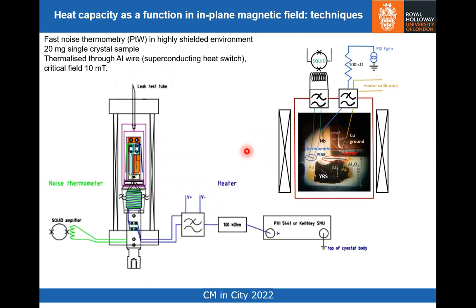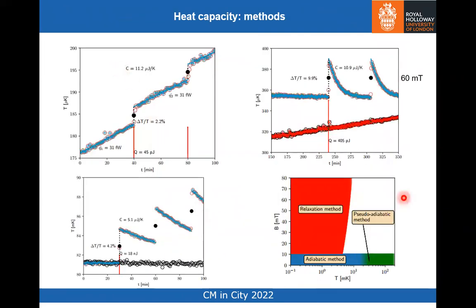So this is primarily a theoretical audience, so I won't dwell on these slides, but we use fast noise thermometry. Noise thermometry has never been used for heat capacity measurements before. It has to be fast, as you'll see in a minute. We're doing measurements on a tiny sample, 20 milligrams. It's thermalized through an aluminium wire, which acts as a superconducting heat switch, which has a critical field of 10 millitesla. So we can take data in a variety of ways that are indicated here.